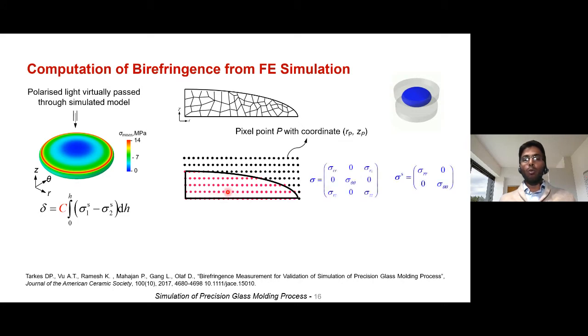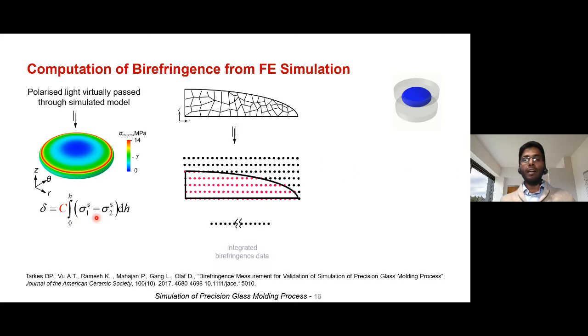And in order to compute the secondary principal stress difference, this is the three-dimensional state of stress for an axisymmetric analysis. From the literature of photoelasticity, one can know that the secondary principal stresses participate in the photoelastic effect. So I have taken the secondary principal stresses to compute this term over here, and once you compute, then you can directly integrate, and then you can get the integrated birefringence data.